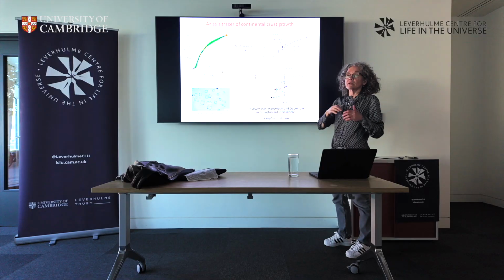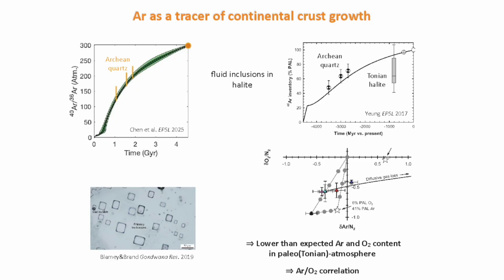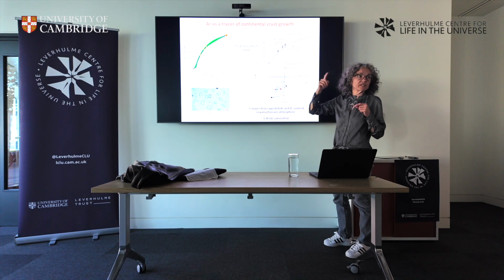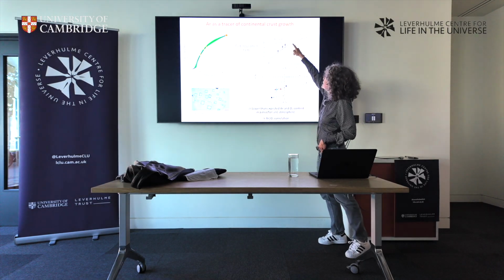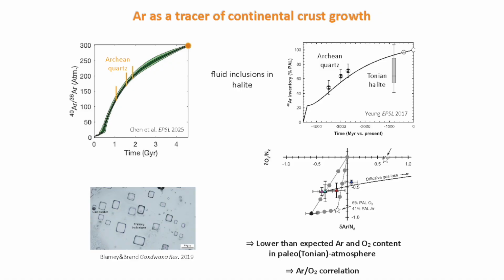For oxygen, it won't surprise you, because 800 million years ago is when oxygen rose in the atmosphere. It's the snowball Earth event, so it's the second oxygen rise in the atmosphere. But it looks like it's correlated with the argon. That's the interesting bit. So in that case, this curve could be revised down so that it goes through this point, and then there should be some massive degassing of argon to go up to the current level.